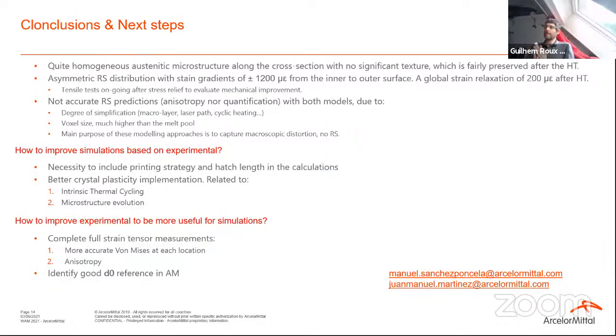Okay, thank you. I have a question for you, Manuel, on the microstructure aspects of your thermal treatment. We know that in additive manufacturing microstructure, you have a strong effect of dislocations. I think that at 700 degrees, you have a strong annihilation in your case on stainless steel. During your thermal treatment at 700 degrees, do you have dislocation annihilation?